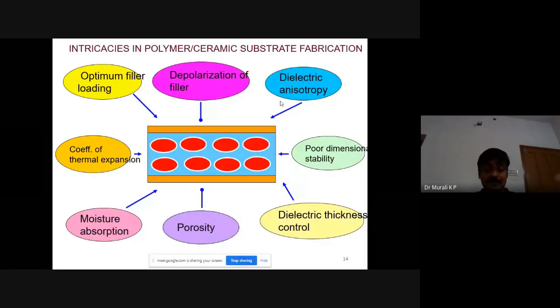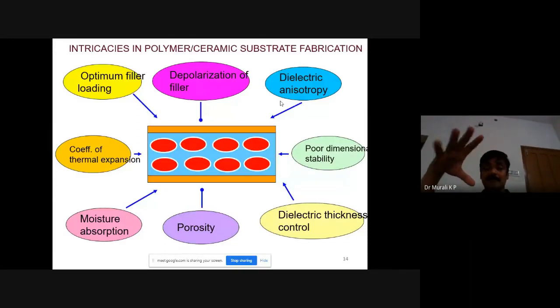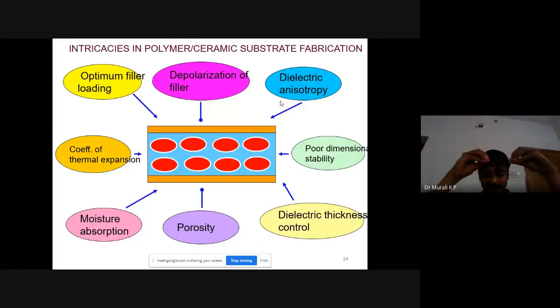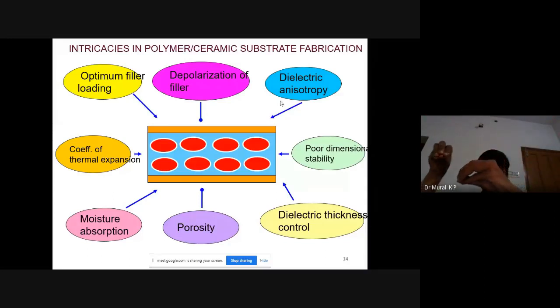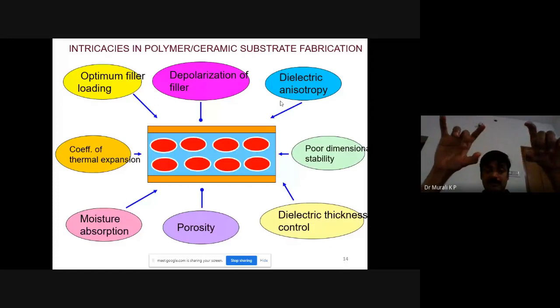Then of course depolarization of the filler, because what actually gives the polarization, epsilon r, is the polarizability of the material. So actually ceramic has got a very high dielectric constant compared to polymer. So when polymer encapsulates these ceramics, they get depolarized. That depolarization has to be controlled, because the ceramic has to be dispersed uniformly. Otherwise, depolarization will be different in different parts of the substrate. So that is why for each polymer and the corresponding ceramic filler, there will be an optimum filler loading which you have to find out for getting the substrate with required properties.